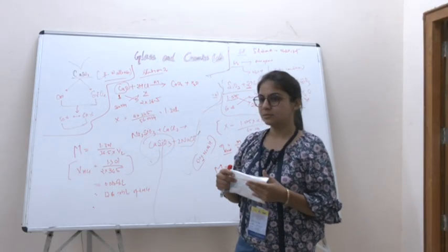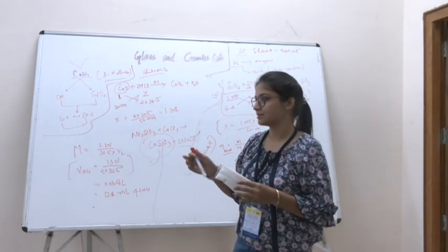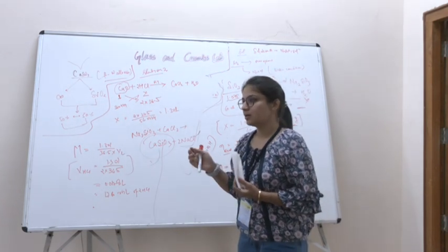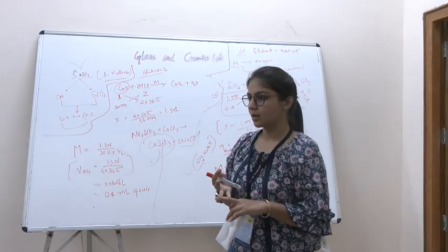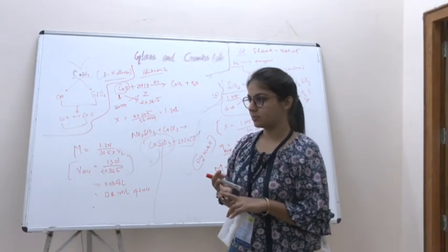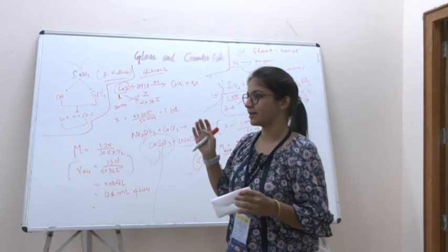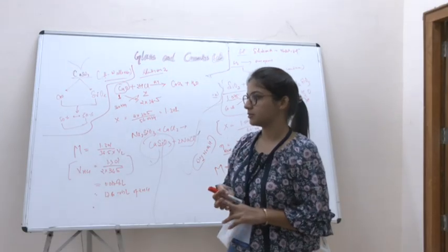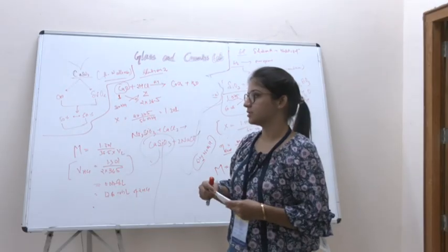Because if you take industrial waste material, as I am using fly ash and GGBS, apart from the calcium and silica source, they also contain iron, potassium, magnesium, and titanium. So that will influence the optical property. Without any external doping, we can enhance the optical property of the material. So this is one of the major advantages of using waste material.